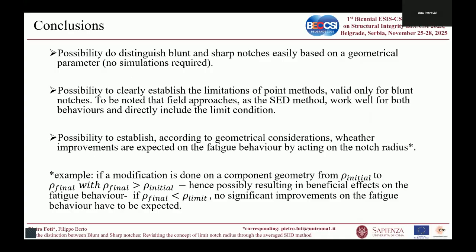To conclude, we have evaluated with this work the possibility to distinguish blunt and sharp notches in an easy way by relying on just a geometrical parameter. So practically, when we have a component, we know the material that we are dealing with. By evaluating this parameter, we can have an idea if we have a blunt behavior, so we can proceed by applying a point-based approach to foresee the fatigue behavior, or if we need to apply a field-based criterion to foresee the fatigue behavior of a component.